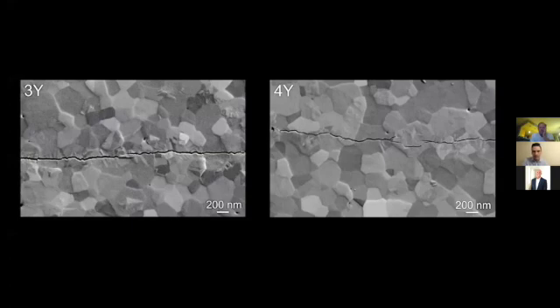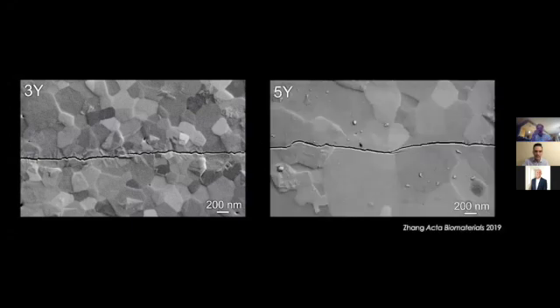If you look at the 4Y zirconia, they push it through, you see transformation, but it travels a while before it does some transformation. And maybe it goes through some cubic zirconia before it gets to tetragonal and is able to transform again. And you can see there's still transformation, though. There's still some magic left in the 4Y zirconias, but not as much as the 3Y. And then if you look at the 5Y zirconia, it's hard to say if there is any, maybe a little bit of squigglies. Most of the magic is gone by the time you get to the 5Ys. So the 5Ys, most translucent, but you're going to be losing out in strength and in transformation toughening.